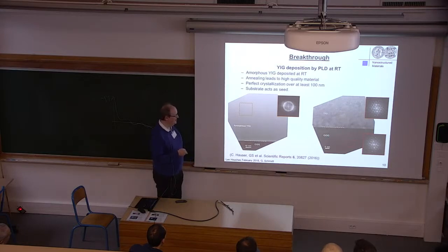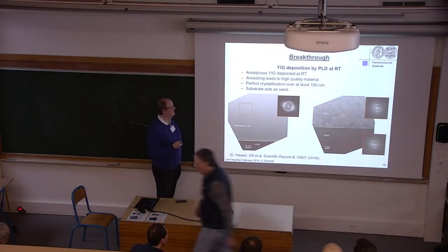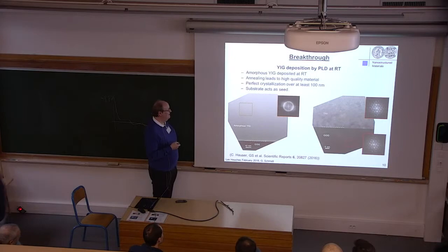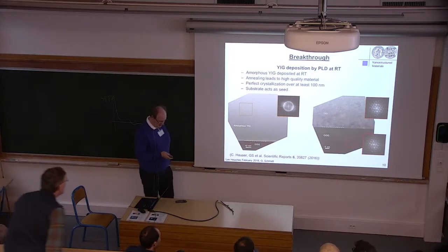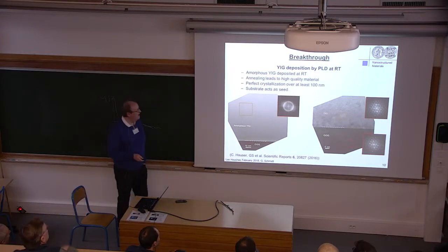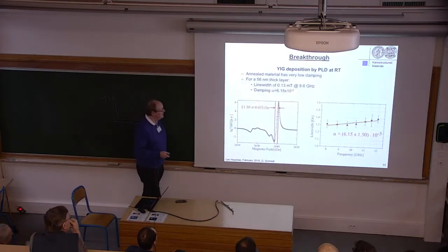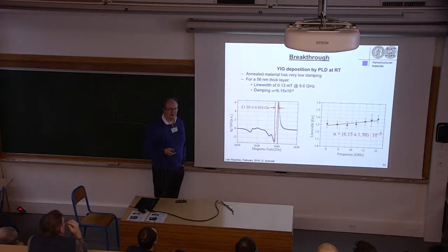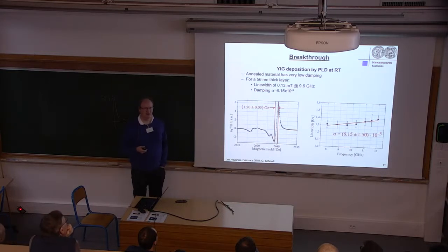So this is GGG and YIG, so standard system in principle. And you see perfect crystallization over at least 100 nanometers in this system. And the substrate in this case acts as a seed. And these layers have astonishing properties, because normally we have already seen some values.